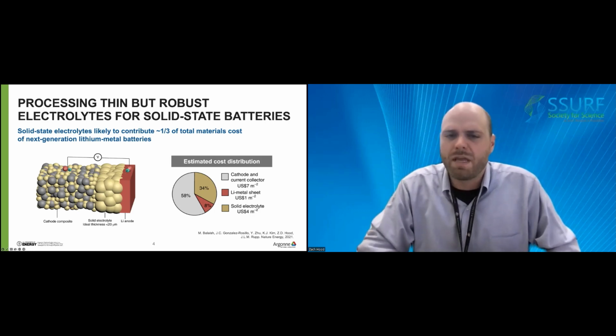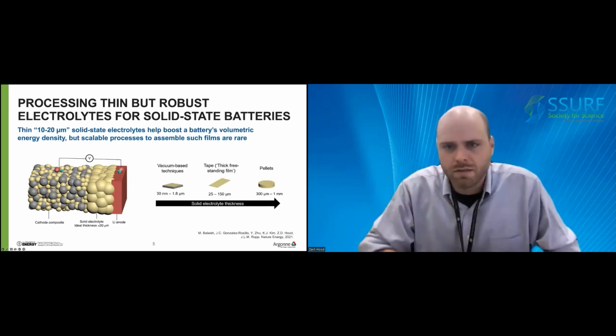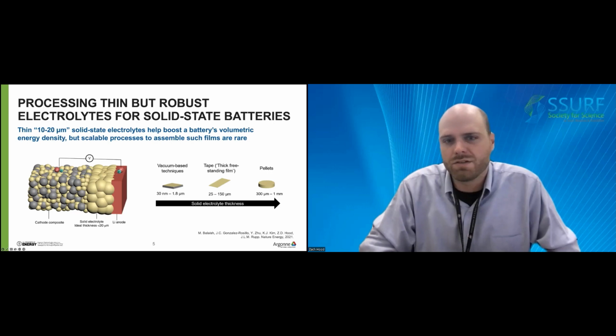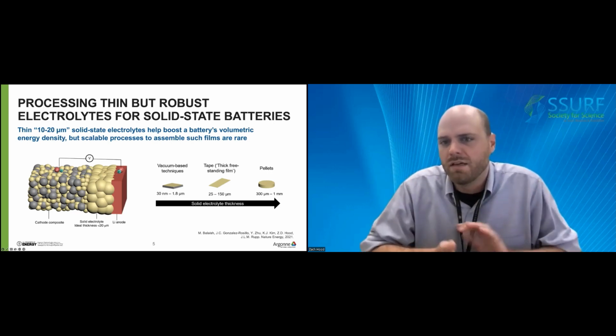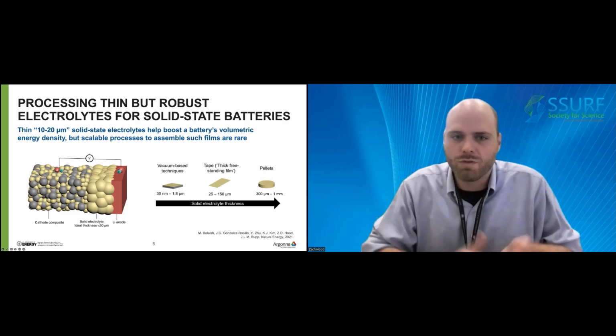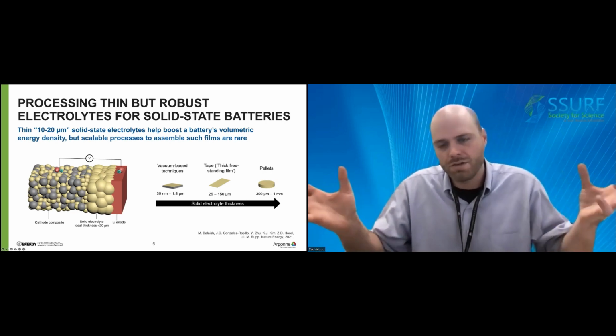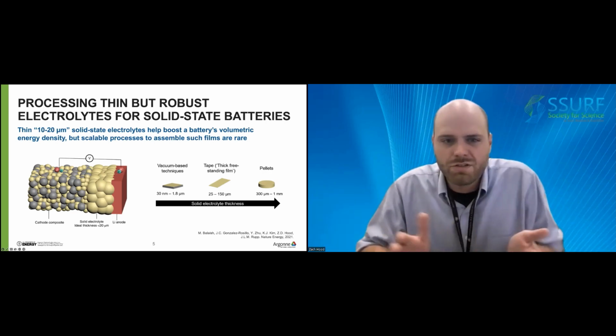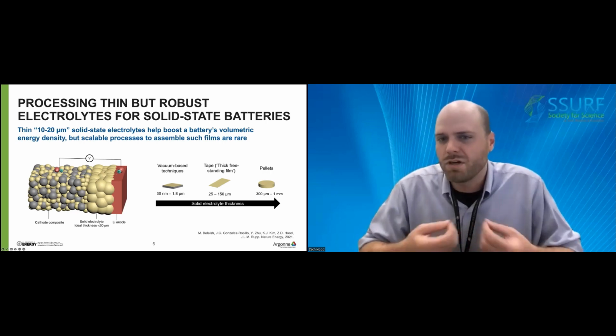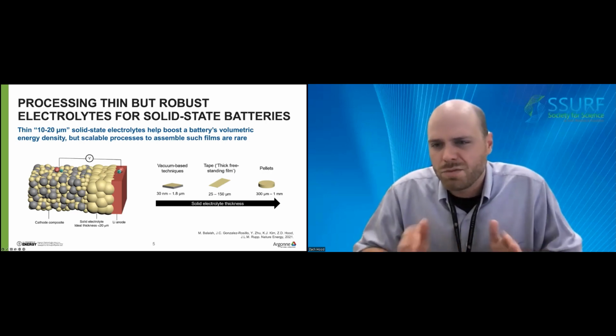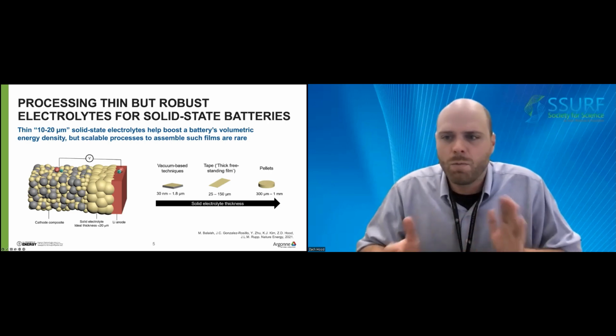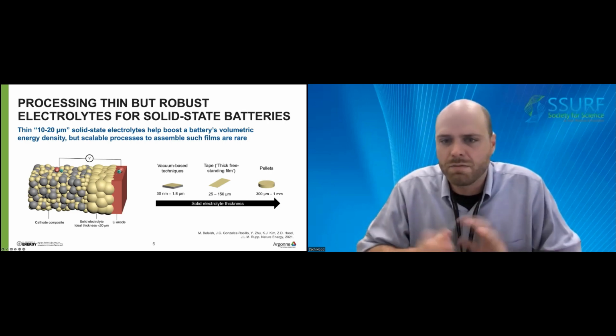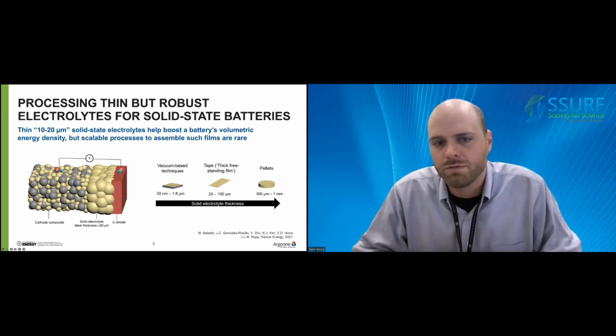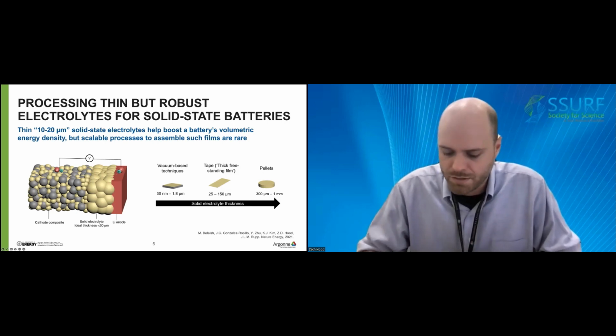So when considering this dimension of 20 microns or thinner, methods to produce our solid-state electrolytes generally yield materials that are either too thick or too thin. Going thick makes your battery have more volume, meaning that you can store less energy per unit volume. And if your electrolyte is too thin, your battery may not hold a charge and it could potentially fail. So there's a sweet spot, again, between 1 and 20 microns in thickness that we really need to target, and urgently, for the United States to have competitiveness in the space of manufacturing.